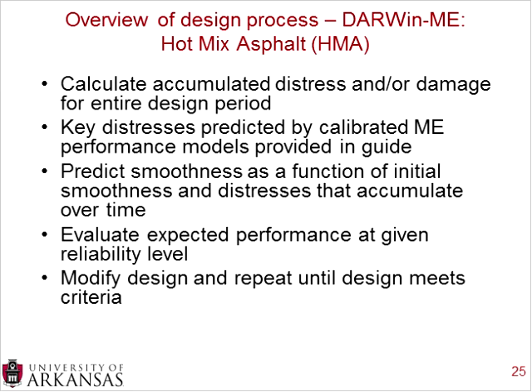So once you know those stresses and strains, you calculate the accumulated distress and/or the damage for the entire design period, and you can predict the key distresses by performance models provided in the guide. So the guide has done a lot of calibration internally, so it knows that based on certain inputs and certain outputs from those inputs, you can predict key distresses. You can also predict the smoothness as a function of the initial smoothness, like the Portland cement concrete, and the distresses that accumulate over time. And finally, you evaluate the expected performance at a given reliability level.